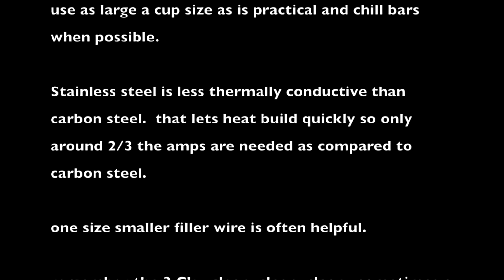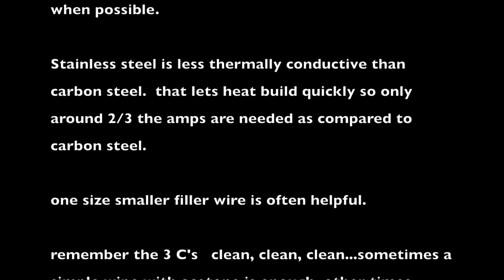Stainless is less thermally conductive than carbon steel. It heats up quickly, heat builds up quickly, and only 2/3 the amps are needed as compared to carbon steel in most cases. Using one size smaller filler wire than you would on carbon steel is helpful. And remember the 3 C's: clean, clean, clean. Sometimes an acetone wipe is enough, other times more cleaning is needed.